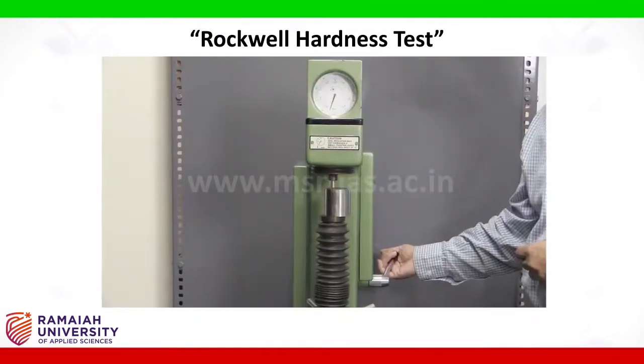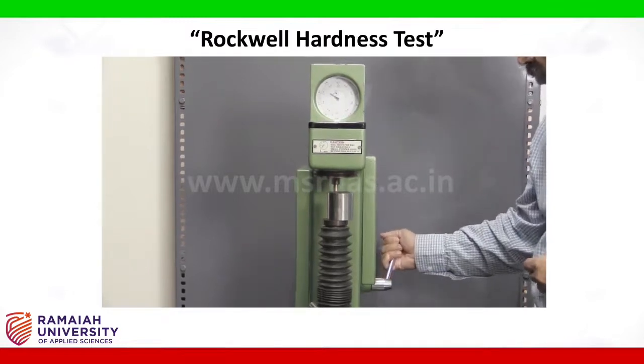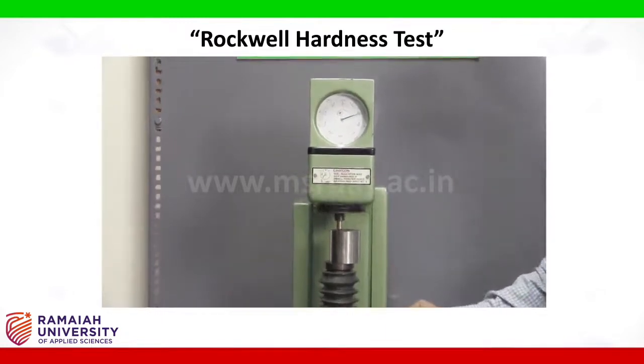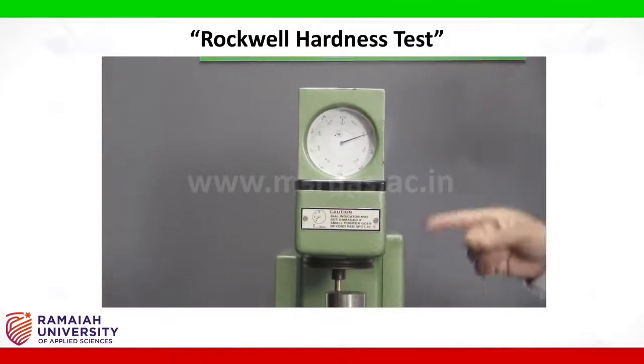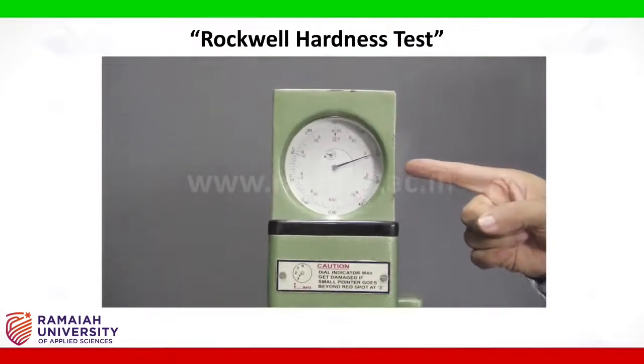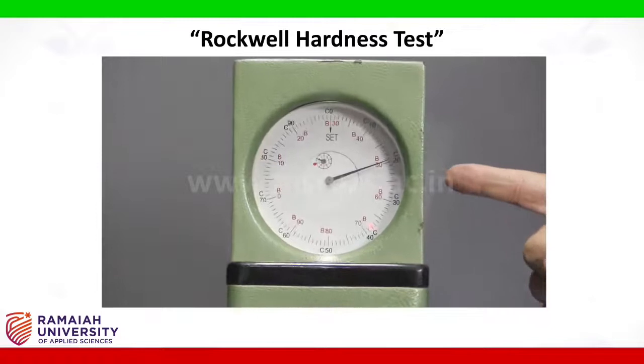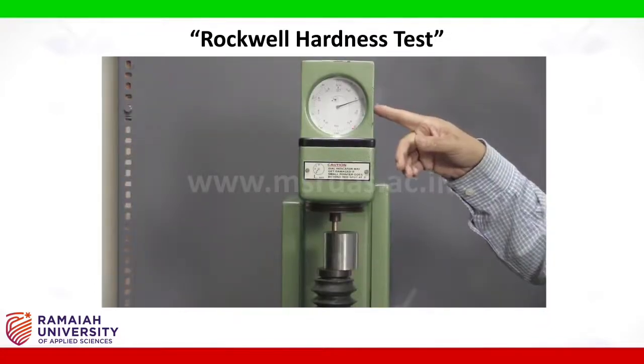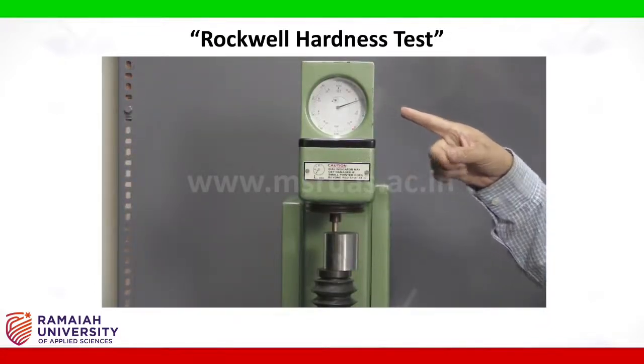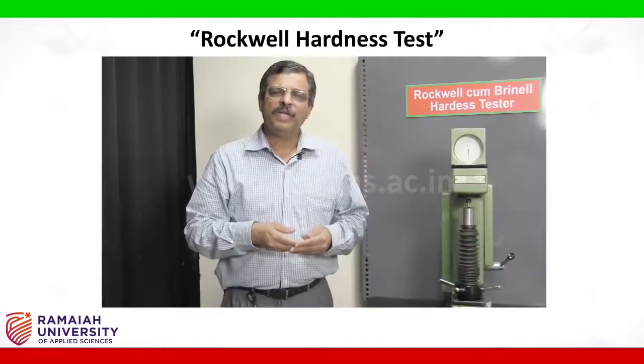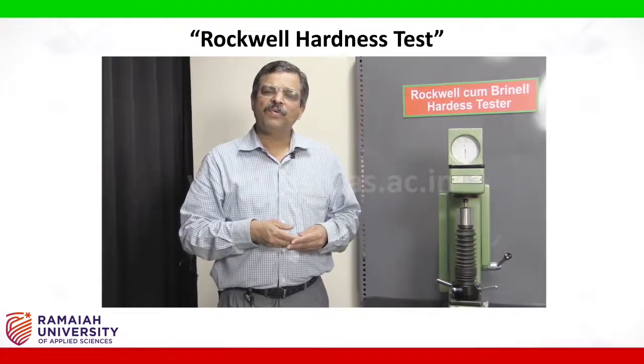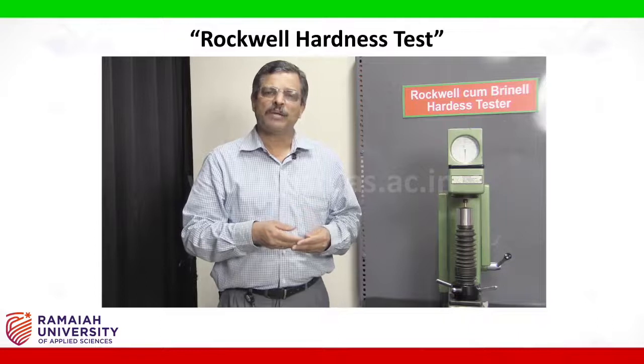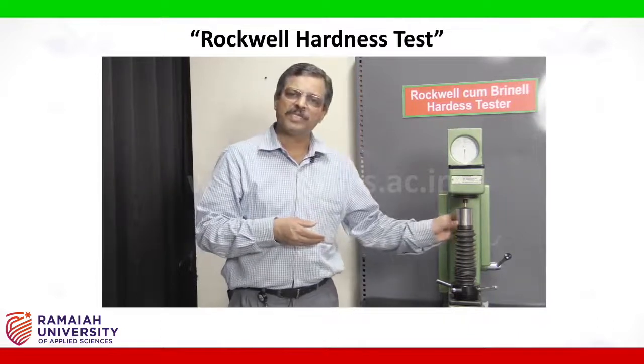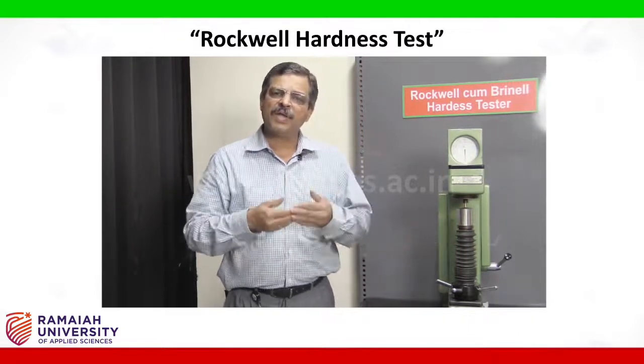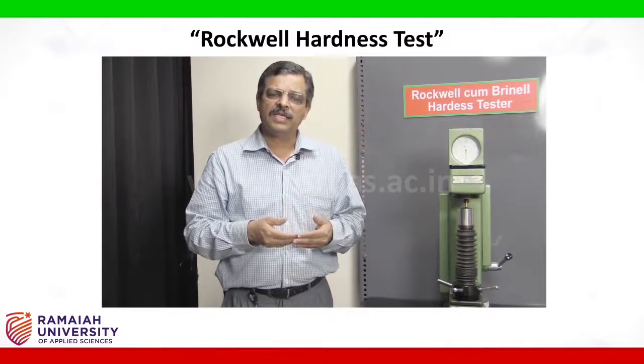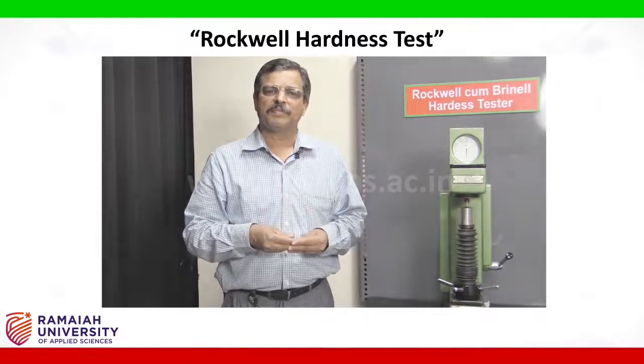Now, after 15 seconds, I am removing the applied load. While I am removing the applied load, please observe the dial gauge. It has settled, the indicator has settled at a particular point. This is the Rockwell hardness number of the considered specimen. To get the final hardness number, I have to repeat the experiment 2 more times at various places in the workpiece and then take the average of all the 3 readings. This completes the experiment.